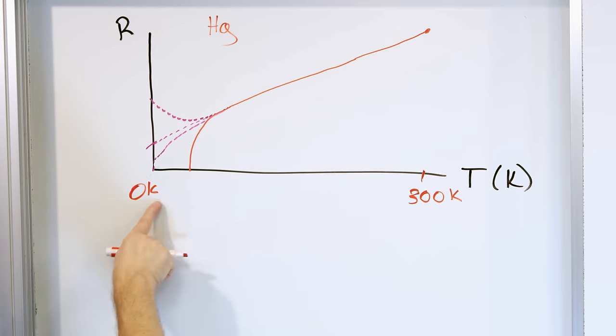And then in 2020, which was at the time of this recording, literally just 2.5, 3 years ago, I don't actually have the entire formula here, but it was a compound with hydrogen, carbon, so not calcium, carbon, and sulfur. One of these days I'll look it up and see what it actually is. Has a critical temperature on the order of 288 Kelvin at 270 gigapascals. Now, 270 gigapascals, I can't even fathom it, okay? This is like the center of Jupiter kind of pressures, all right?